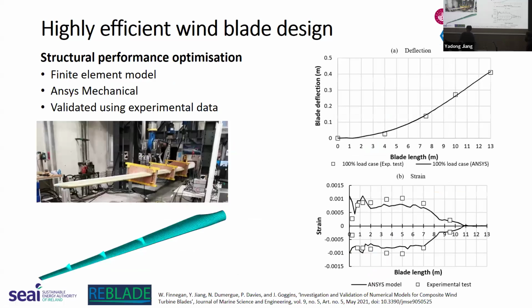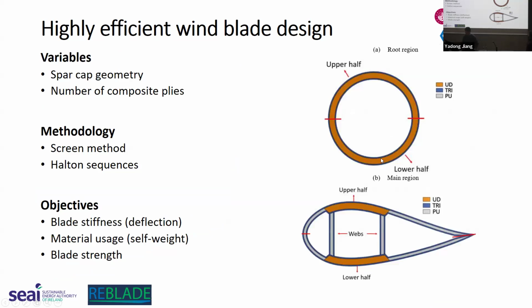After we got the external shape of the blades, we tried to design its internal structures. Here we use the ANSYS software as we used before. Besides validating the model using the testing data from the demonstrator, we also utilized the testing data we obtained from the previous testing of a full-scale 30 meter blade to further validate the numerical model. We got good results in terms of the deflection and strain, which enhanced our confidence in this finite element model.